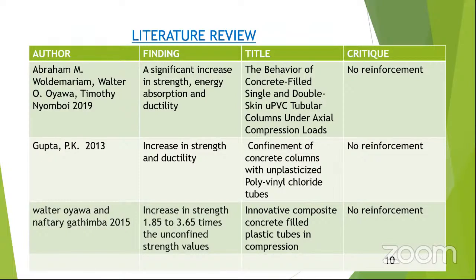The next researcher was Gupta in 2013. He did confinement of concrete columns with unplasticized polyvinyl chloride tubes, and his finding was an increase in strength and ductility. The third research was in 2015, by Walter Oyawa and Naftaly Gathimba, and their title was Innovative Composite Concrete Filled Plastic Tubes in Compression. The finding was an increase in strength, 1.85 to 3.65 times the unconfined strength values. The critique in all these researches is we believe that they experienced failures due to lack of reinforcement. So that is the difference in our research.